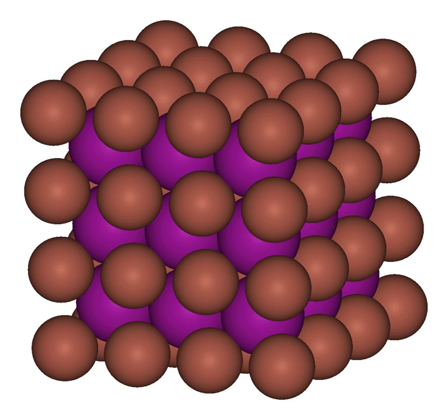Thallium III fluoride complexes. The salts NaTlF4 and Na3TlF6 do not contain discrete tetrahedral and octahedral anions. The structure of NaTlF4 is the same as fluorite, calcium fluoride, with Na and Tl III atoms occupying the 8-coordinate Ca sites. Na3TlF6 has the same structure as cryolite, Na3AlF6. In this, the thallium atoms are octahedrally coordinated. Both compounds are usually considered to be mixed salts of Na+ and Tl3+.